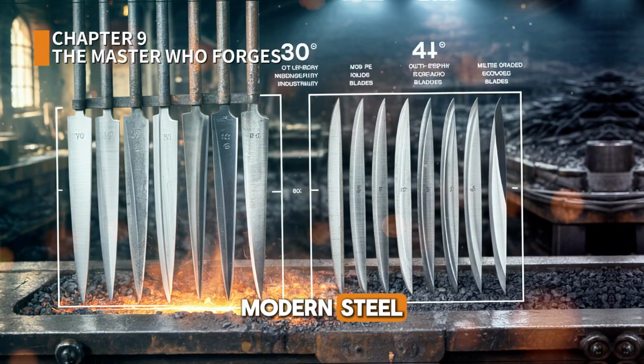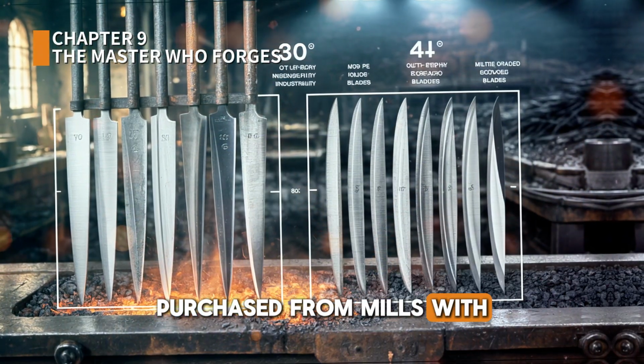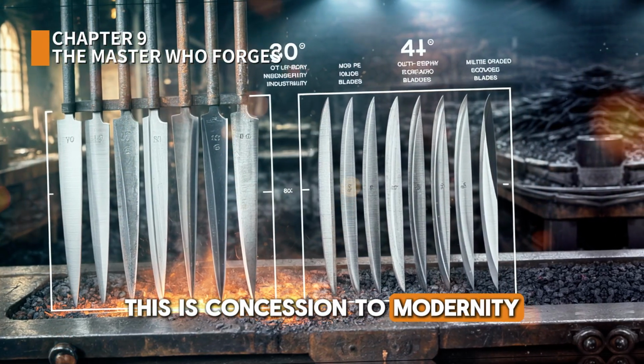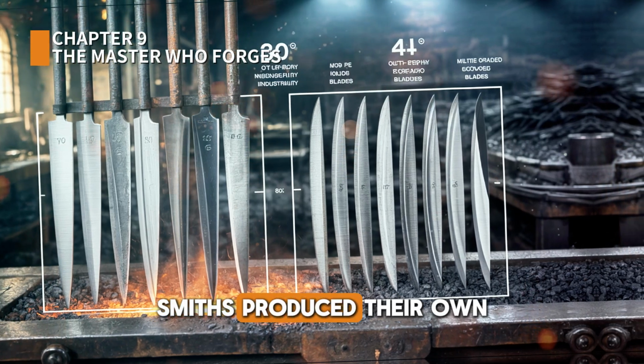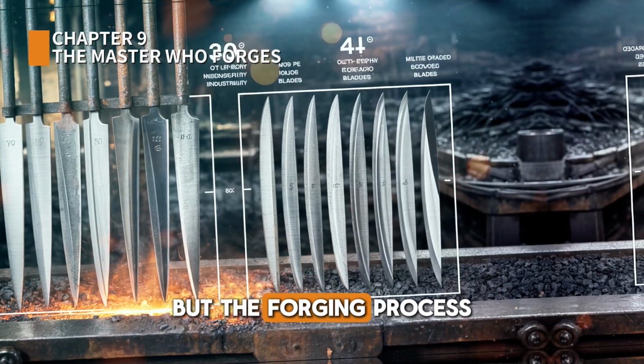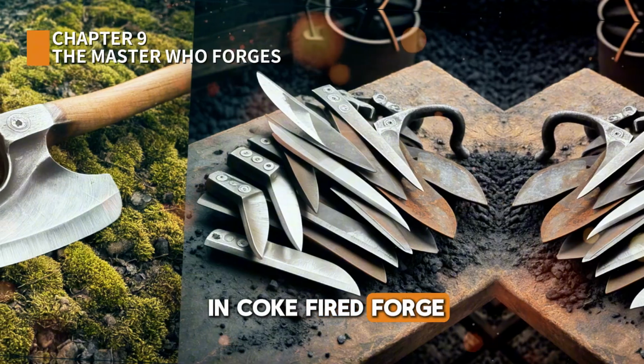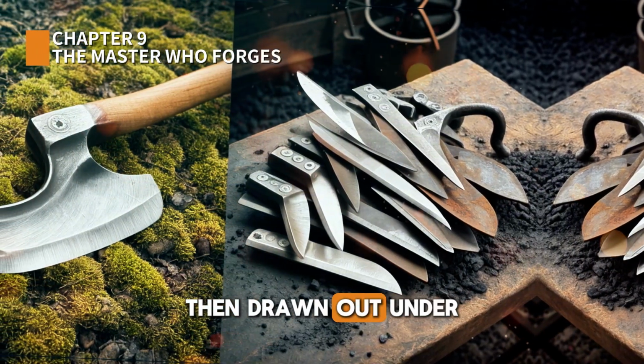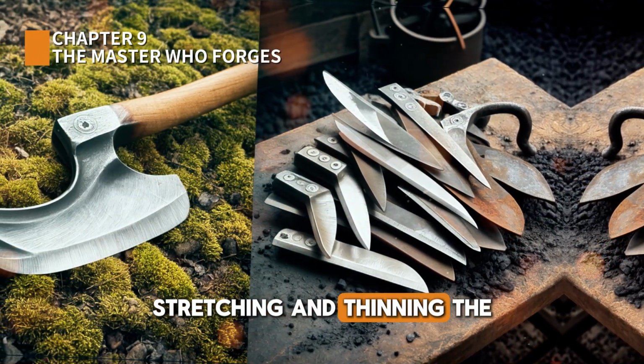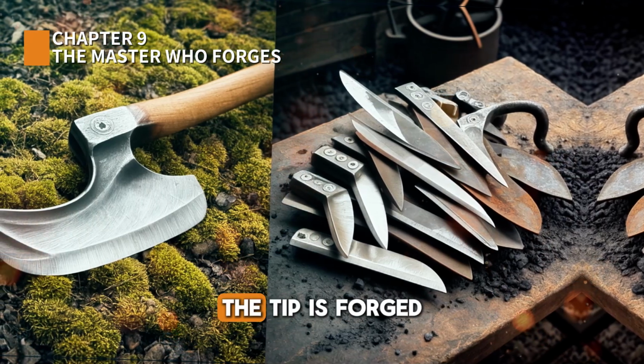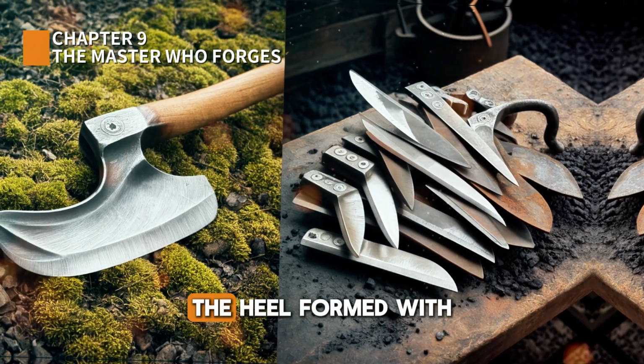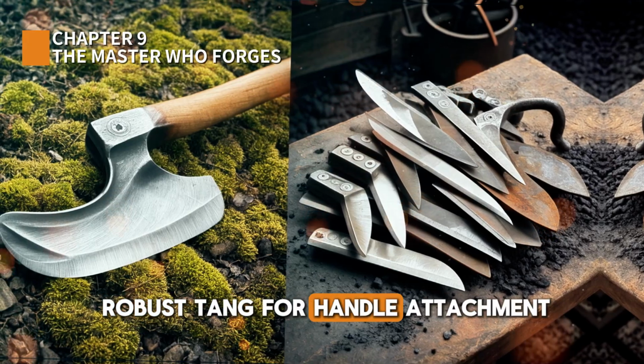The process begins with steel bar stock, modern steel, purchased from mills, with specified carbon content. This is a concession to modernity. Historically, smiths produced their own steel through time-intensive carburization, but the forging process is traditional. The steel is heated in a coke-fired forge to yellow heat, then drawn out under power hammer blows, stretching and thinning the material into blade shape. The tip is forged to a delicate point, the heel formed with a robust tang for handle attachment.